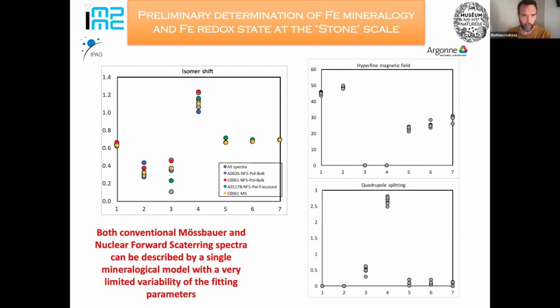These are the parameters derived. As you can see, all the data can be fit with a bunch of parameters that are pretty much the same and pretty consistent with what was derived for grain 61 in conventional Mossbauer, the plot in the orange diamonds all around. The only variability is for the isomer shift of this line that corresponds to iron 3+. And so we'll discuss this a little bit later.